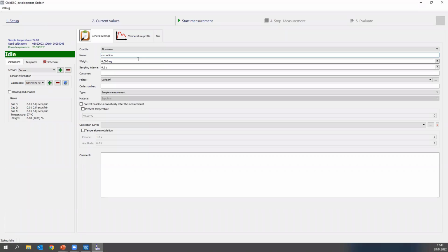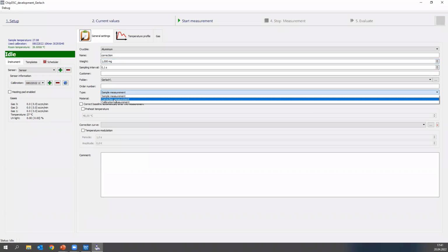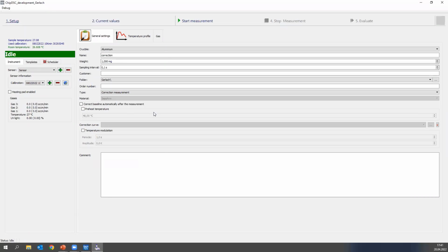With the correction, the weight doesn't matter, so 0 milligram or for example 1 milligram doesn't matter. The software ignores that for the correction measurement. Then the sampling interval of 0.1 second is quite okay. We have no customer, this is my folder, and there's no order number. But what we have to change is we want to do a correction measurement. And now we can already see we are not allowed to choose any correction curve anymore. And this is what's important.